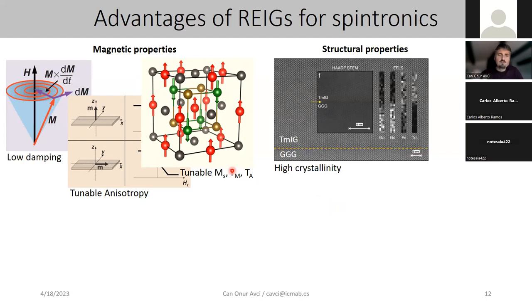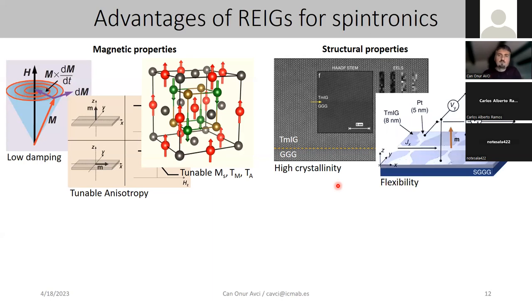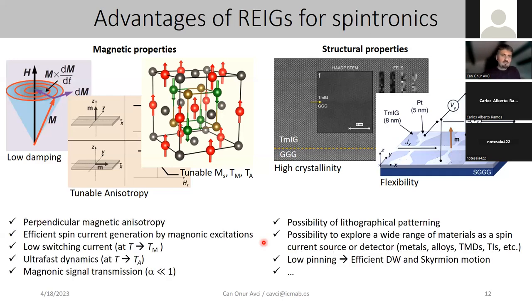On the structural side, they are grown epitaxially on GGG, so they have a minimum amount of defects in the crystal, which makes them very appealing from the reproducibility and technological aspects. They also give you some flexibility in terms of device design, because since these are natural oxides, they are not affected by the environment, so they don't get oxidized or anything. They don't age easily, so I can still measure my samples from 2016 and they are in perfect condition. So that's why you can also put some metallic bars in random positions and just probe that specific location electrically without doing any complicated patterning. So all these aspects are giving rise to multiple advantages I'm listing here for spintronic applications.